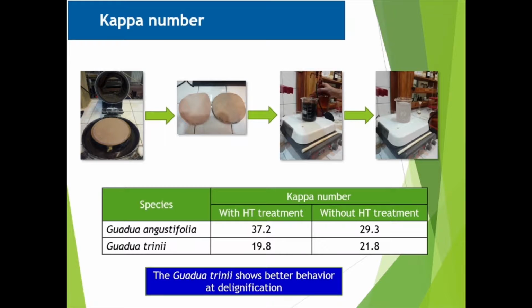Kappa number indicates an indirect relationship of the pulp with the residual lignin. We can observe that there are differences between species and with and without hydrothermal pretreatment. We also see that Guadua trinii presents a better delignification behavior, having lower kappa number values in both cases.